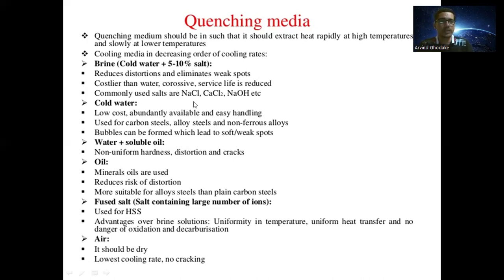Commonly used salts are NaCl (sodium chloride), CaCl₂ (calcium chloride), and NaOH (sodium hydroxide). The second cooling media is cold water, which has low cost, is abundantly available, and easy to handle. It is generally used for cooling carbon steel, alloy steel, and non-ferrous alloys, though bubbles can form leading to soft or weak spots.